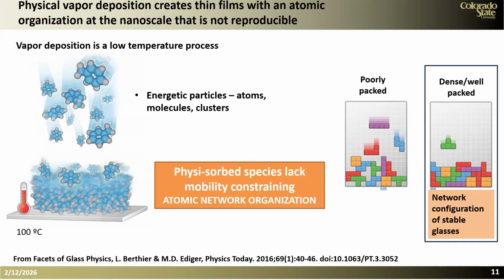And the way to think about it is that these are tetris materials, and you see here a tetris picture in which these are the atoms and molecules that land, and they are very disorganized, and therefore they will give you a material that is poorly packed. But if we can control that, then we could get a network that is more densely packed. And this densely packed network is characteristic of what are called stable glasses. Stable glasses are grown in nature by cooling the liquid very, very slowly.